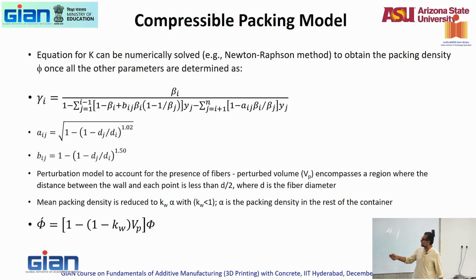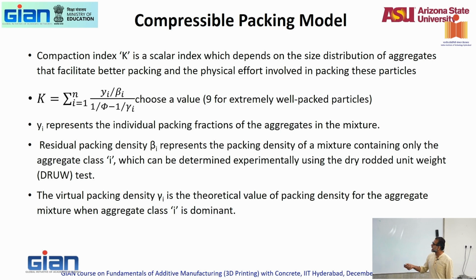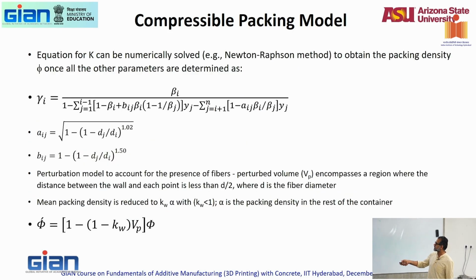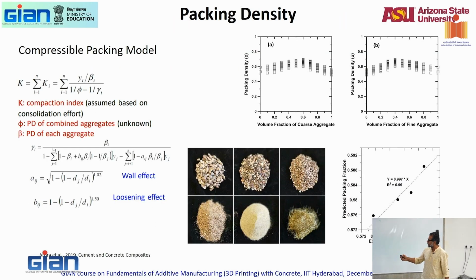And then you can use an optimization method, a Newton-Raphson method, for example, for those who have done a numerical methods class. You can use that to find the value of gamma i based on this. And then if you have fibers in it, your fibers will also perturb the volume. Fibers are long. They'll also try to move the materials farther apart. You can account for the perturbation volume. All of it said and done, here is, so if I'm using these different aggregate sizes, 1, 2, 3, 4 different aggregates, sand, fibers, all of that, here is your simulated model.